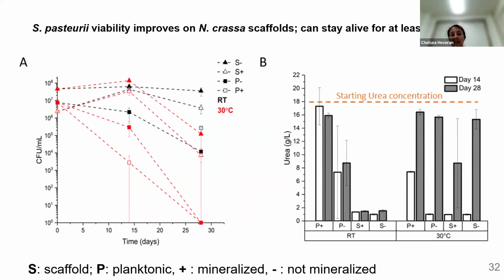We also asked whether the bacteria would stay alive this way, if they like to stay alive when they're on Neurospora crassa scaffolds, and the answer is yes. In this key, S is scaffold, P is planktonic, meaning no scaffold, plus is mineralized, and minus is not mineralized. On the left, when we have planktonic conditions, no scaffold, if we dry planktonic cells for 2 or 4 weeks, they're dying. By 4 weeks, they're dead. That makes sense. When they're on a scaffold, they're not dead.